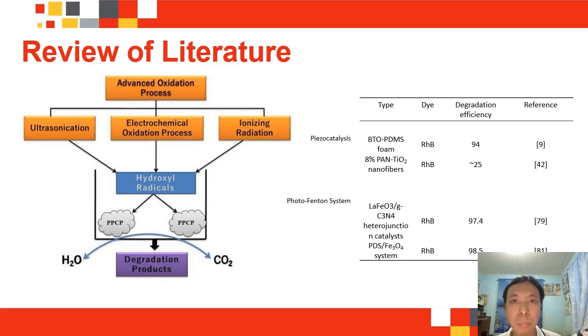So for the table, we have different fabricated materials utilizing AOP. For the foam, BTO-PDMS, the efficiency reached 94%, while an 8% PAN-TiO2 nanofiber reached a degradation efficiency of 25%. Then materials utilizing photo-Fenton systems such as the LaFeO3, g-C3N4 heterojunction catalyst reached a degradation efficiency of 97.4%, while the PDS Fe3O4 system reached a degradation efficiency of 98.5%. So we can see that the photo-Fenton system is super effective compared to the piezocatalysis, but requires acidic conditions and post-treatment to remove Fe ions.